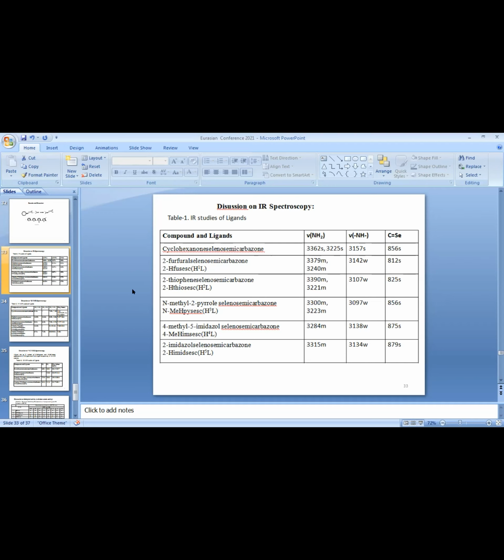For example, in cyclohexanone selenosemicarbazone, the peak that appeared near 3362 cm⁻¹ is NH2, and NH appeared at 3157. The bond between the carbon and the selenium shows stretching bands near 856, and other peaks. If we compare with the ligands, 2-furfural selenosemicarbazone, 2-thiophene, N-methyl 2-pyrrole, 4-methyl 5-imidazole, 2-imidazole, these peaks indicate that the compound as well as the selenosemicarbazone ligands have been prepared.